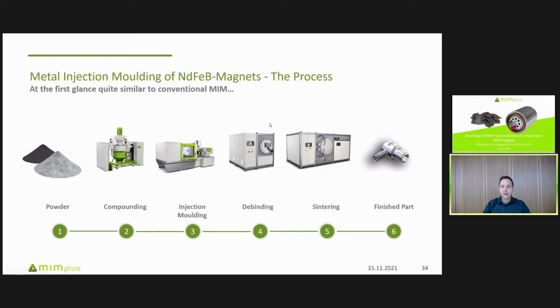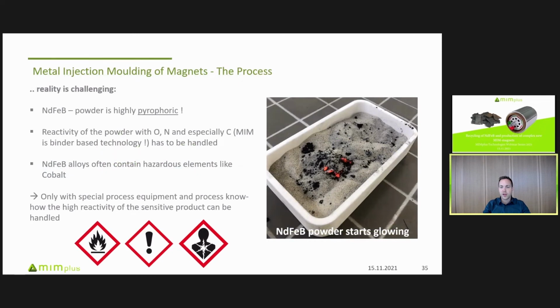At first glance, this process can be quite easily transferred onto neodymium iron boron, but in reality, it's quite challenging because neodymium iron boron is highly pyrophoric if you use small powder. So it starts to burn, it starts to glow at room temperature, if you don't protect it, for example, with inert gases or appropriate containment systems. And that reactivity of the powder with oxygen, nitrogen, also carbon, makes the MIM process quite critical for working with that powder.